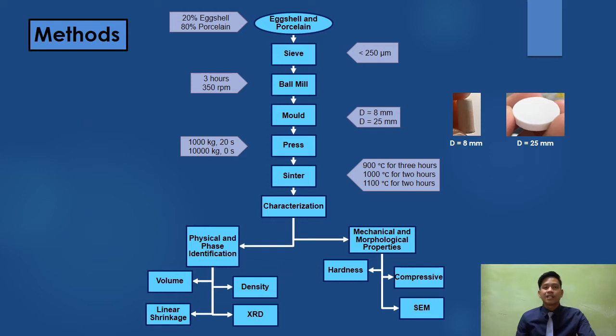The physical characteristics such as volume, density, and linear shrinkage are deemed significant since they might affect the filtration system's efficiency. XRD analysis was used to identify any unidentified crystalline phases produced by varying sintering temperature with the measurement conditions of 40 kV and 40 mA X-ray, 2 degree per minute for scan speed, and 2 theta scan axis with a scan range of 10 to 80 degree. For the mechanical and morphological properties, the Shore hardness was applied to test their hardness.